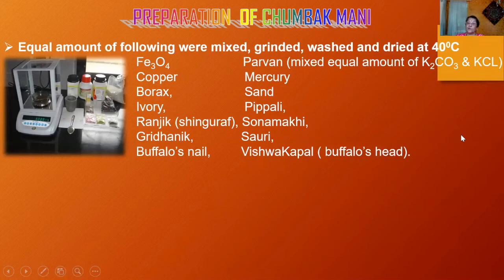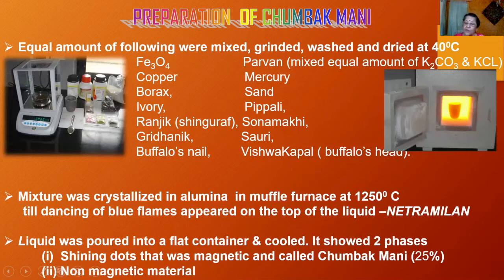Now we didn't know, because they don't mention the temperature up to which we should heat. What they said was, you should heat till you get the netramilan. And what is netramilan? The whole thing starts becoming liquid, and on top of the liquid some blue dancing flames appear. We realized that to get netramilan, 1250 degrees centigrade was needed. It was very difficult because many things we know today, how we are taught today, were very different at that time. They were describing the temperature at which you start receiving netramilan, and we realized that it is 1250 degrees centigrade.